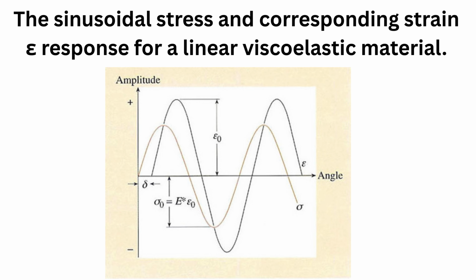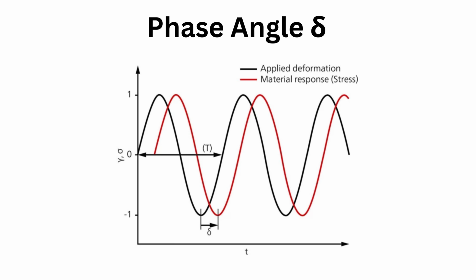Stress analysis concerned with the dynamic mechanical properties normally assumes that polymers are linearly viscoelastic. The strain response lags behind the stress by the phase angle, owing to the viscous component of the material. Some, but not all, of the energy stored during the deformation of the material is dissipated. Since the material is assumed to be linear, the stress is proportional to the strain at all times, that is, sigma equals E epsilon, but E is a function of the frequency omega. Because the stress and strain are not in phase, E must be treated as a complex function.